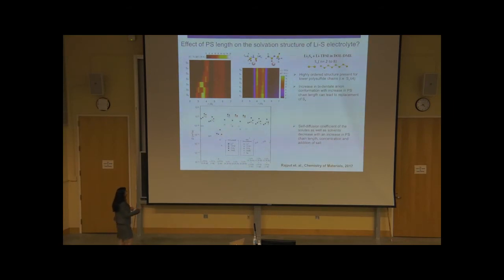And we looked at the effect of the solvation structure on the diffusion of different ions present in the solution. We checked three things. The first is that if we just take a lithium TFSI salt and increase the concentration to 3 molar, we significantly decrease the mobility of ions. So there is a limit up to which you can increase the concentration of lithium TFSI salt in the solution.